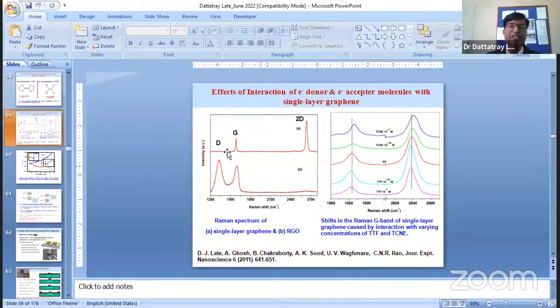two kinds of samples: single layer graphene, which is transferred by micromechanical exfoliation, and another sample which we have in solution form, that is reduced graphene oxide. And we have recorded the Raman spectroscopy of pristine graphene or reduced graphene oxide, and we started adding different concentrations of TCNE and TTF.